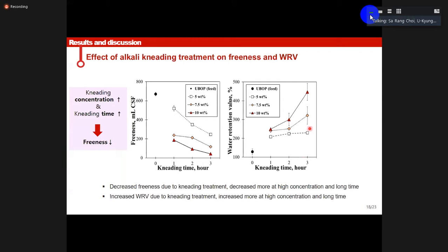The graph on the right is about water retention value. The y-axis is the WRV and the x-axis is kneading time. The kneading treatment increased the WRV of the fiber. The higher the concentration and the longer the time, the higher the WRV. Especially, the sample kneaded for 3 hours at 10% concentration showed the most reduction of freeness and the best water holding capacity.